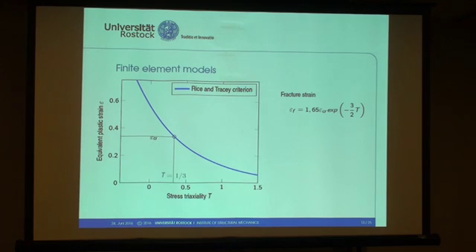Also, a failure criterion is used to reproduce the fracture or failure in the weld joint. I used the Rice and Tracey criterion. It's a function of the plastic strain, depending on the stress triaxiality. The stress triaxiality is calculated from the hydrostatic stress state and von Mises equivalent stress. And you can see here the curve of the failure criterion.